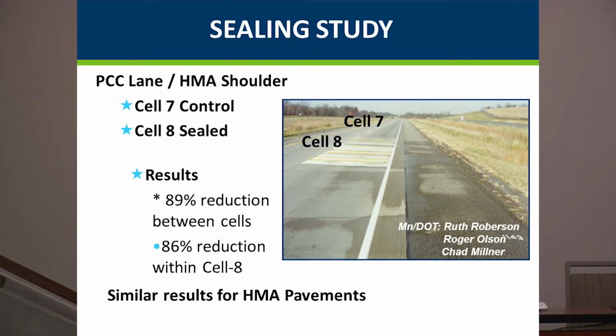But this one's really kind of nice because it shows the effects of when you do seal roadways. And I know this is a concrete road, but you can see up above there, it rained, the water is flowing off here where the sealant is. Where the sealant's not, the water flows right into the joint. And we saw this for asphalt and concrete because we had tipping buckets measuring the outflow of all these test sections. And we saw that you can get about an 89% reduction in water if you do stuff like that. It's just sealing that edge, if it's a longitudinal joint, an asphalt or a concrete joint, that's quite a big deal. And that really moves the water off to the side.